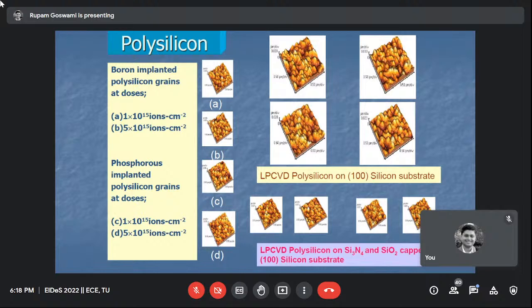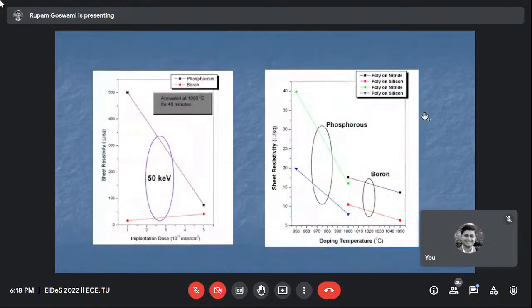Next, please. Particularly in this slide, you can see that if LPCVD polysilicon is deposited over an insulating substrate or silicon substrate, it makes a lot of difference to the grain size. But in this particular case, we need isolation of each resistor so that crosstalk is minimized. That is the requirement, and that's why either silicon dioxide or silicon nitride or a combination of both should be there while depositing polysilicon.